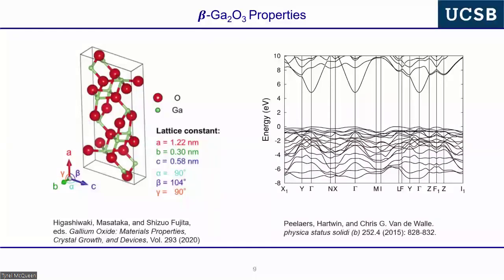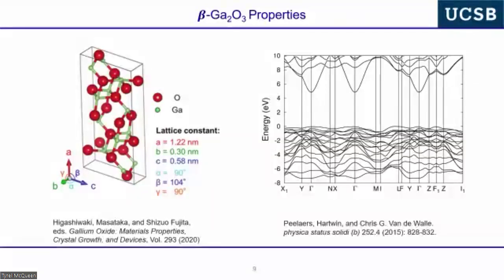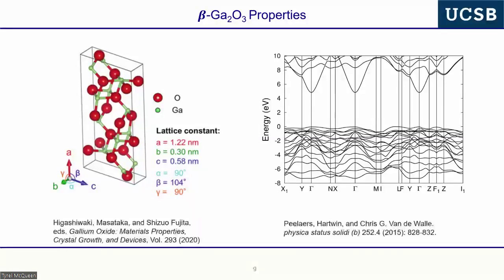Something else we'll talk about today is the E-k diagram. And so this is in reciprocal space, and this is just in different directions in the Brillouin zone. Again, this spaghetti down here is because of the complicated crystal structure, okay? And so you go directly from orbitals to bands, and because you have low symmetry, you have a lot of bands, okay? And the highest occupied bands are the valence bands. And on the landscape of the E-k diagram, this is approximately flat, okay? And the curvature of the bands directly determines 1 over the effective mass of carriers. And because the bands are flat here, if we had holes in beta gallium oxide, they would be extremely heavy.